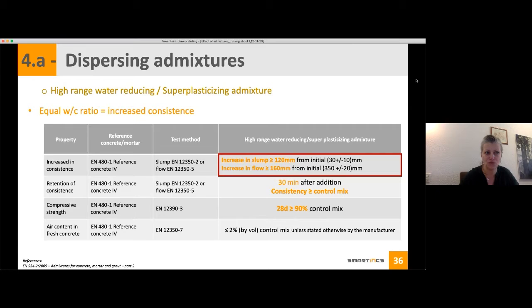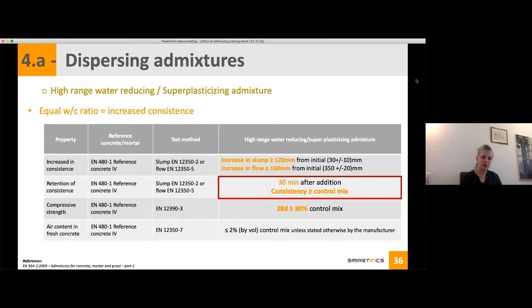That would be in that case 30. And if you talk about the flows, then it will be an increase of 160 millimeter compared to the reference, that will be 350. So you see that the effect is really big. But the superplasticizer is not increasing consistency only. You should also show some retention, or they also bring some retention of consistency. And the requirement for superplasticizers is that 30 minutes after the addition, the consistency of your mix should be at least the same as your control mix. It could be higher, but cannot be lower.